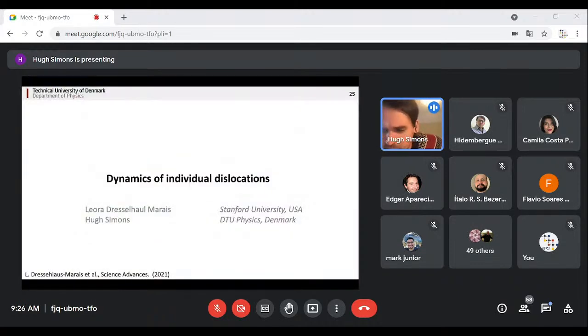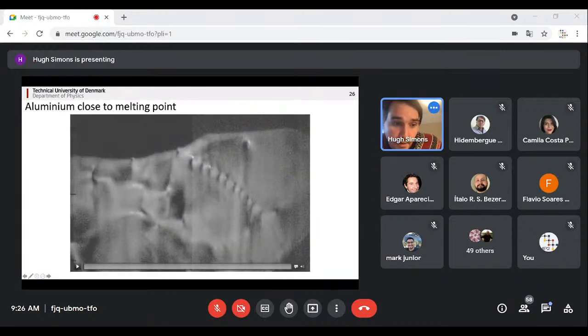At this point, we were getting pretty confident with our abilities to visualize dislocations. And so at this point, we started working with a collaborator now at Stanford. And she was interested in if we could capture really the dynamics of dislocations. And she had a piece of aluminium that she heated very close to the melting temperature. And you can see this is, in fact, the low angle grain boundary consisting of individual dislocations.